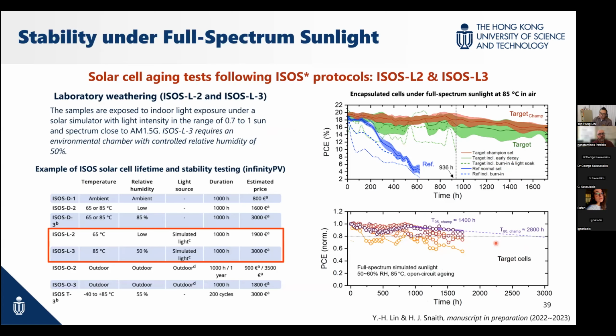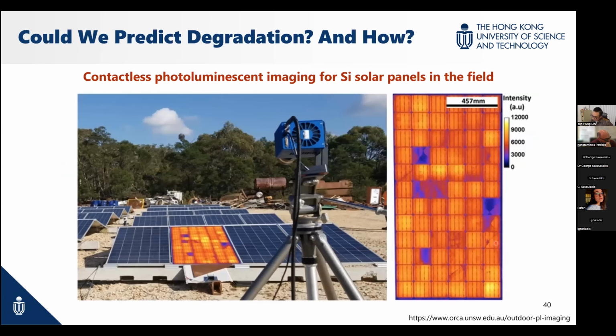Okay, so by using this kind of interface modification, we achieve even better performance. Our device can survive at 85 degrees in air, encapsulated, and especially for our champion cell, it's 1500 hours to reach T95. All right, so we are approaching the last part, just a couple of minutes more.